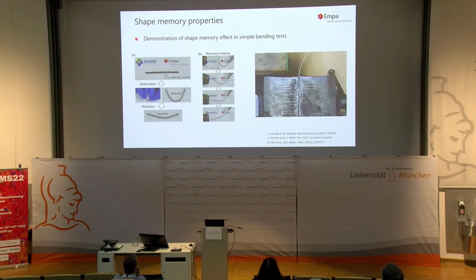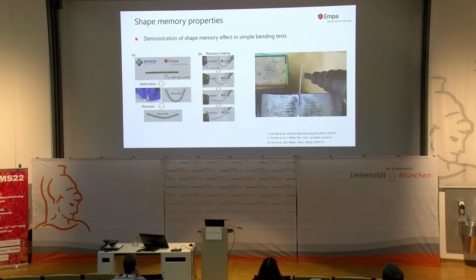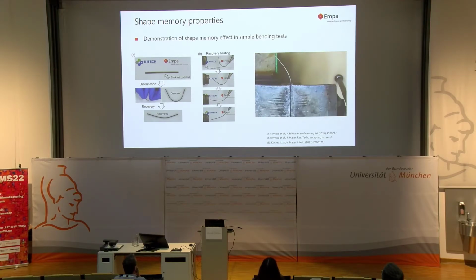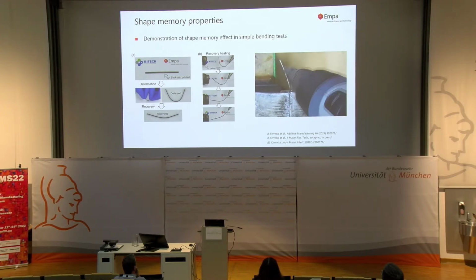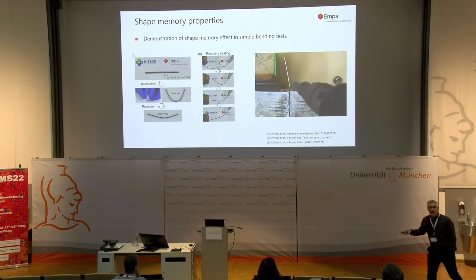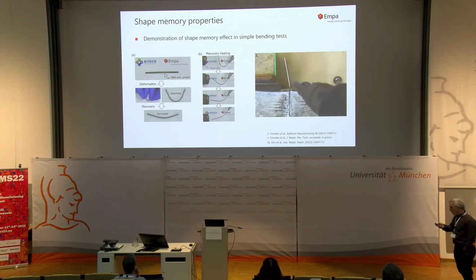Good, what we wanted to know, shape memory effect. So we did the most sophisticated experiments, as you can see here. Simply bending and heating it, that's the fastest you can do. And you can see in these bending tests we get fairly nice recovery, so here in real time. So it is a shape memory alloy after all.